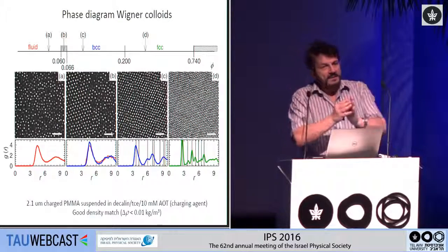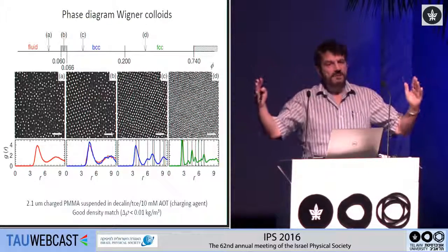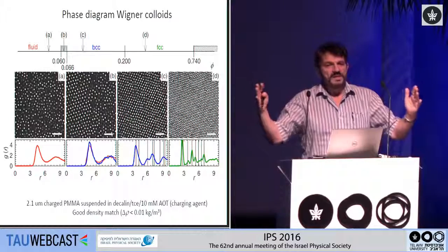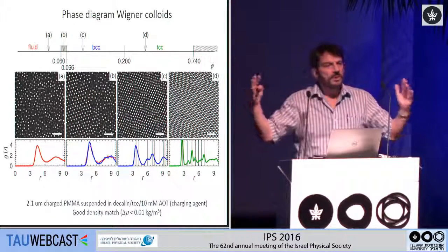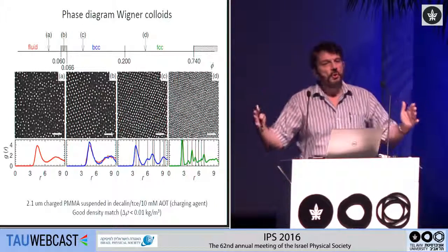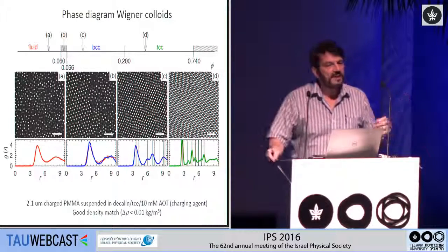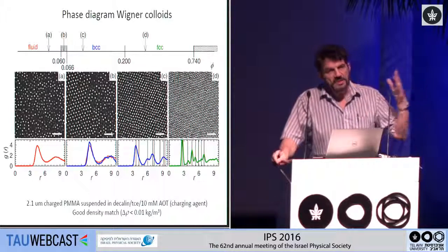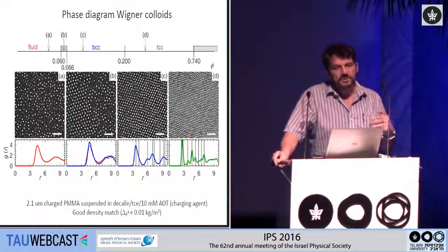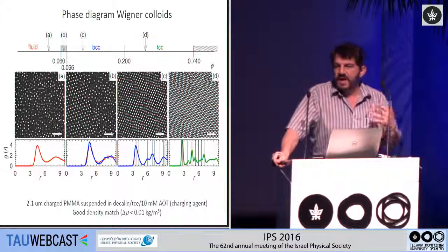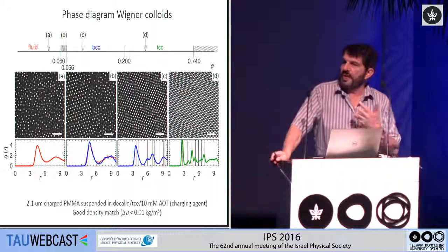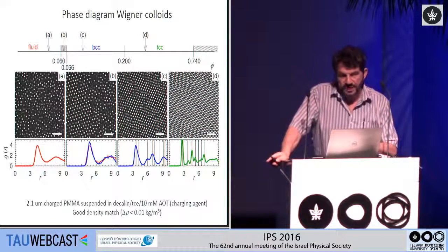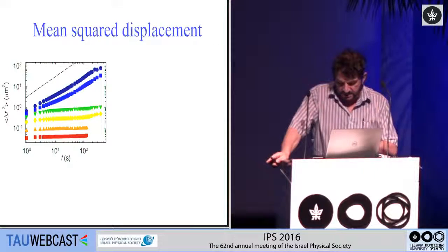So again, the system is held in place by the walls of the sample container. So you can look across the whole system and you see no defects. It's a perfect lattice across the whole system. So this is really the infinite system and allows you to look at this question of what happens in melting when you don't have an interface, to address this issue that Born was discussing.